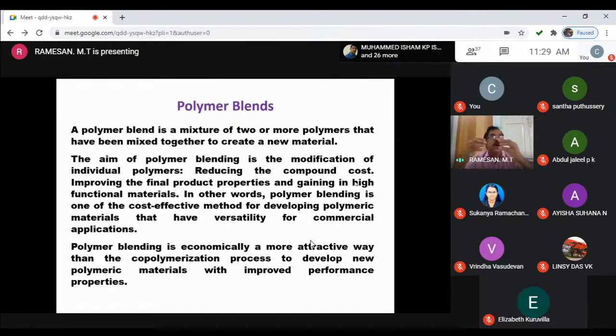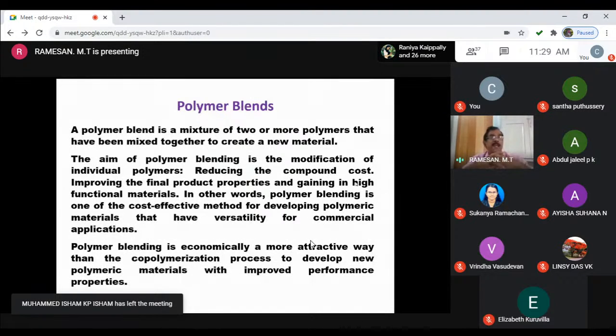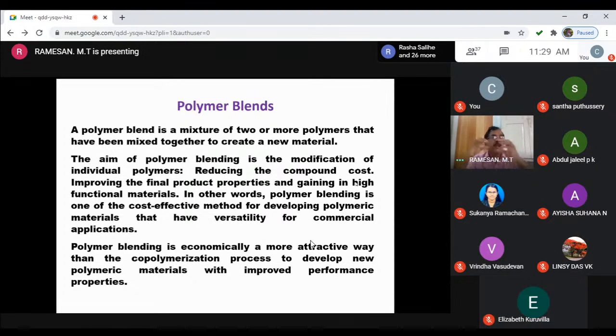Another advantage of polymer blending is that we can improve the processability of the polymer system. For example, polyphenylene oxide, abbreviated as PPO, has a glass transition temperature of 210 degrees Celsius, and that polymer is processable only at a higher temperature. So we want to make that material easily processable by blending with polypropylene or polystyrene. For example, polystyrene has a glass transition temperature of 100 degrees Celsius. So when we mix polyphenylene oxide with polystyrene, we can reduce the temperature, meaning we can easily process that material. That is the advantage of polymer blending.